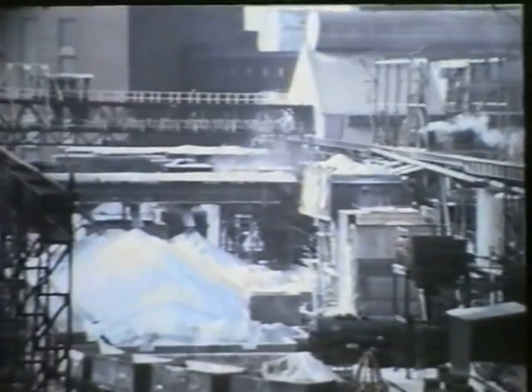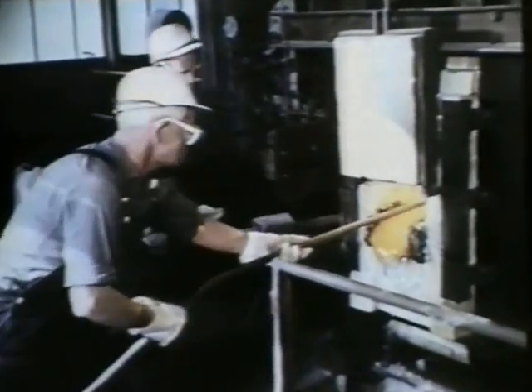Over the road from the bicarb plant, here's something interesting. A heap of green glass, but it's soluble in water, and from it is made one or other of Winnington's many sodium silicate solutions. The silicate glass is made by fusing sand with soda ash in a furnace. It's just been opened up by John Hulse. Joe Goff rakes out the molten glass at a temperature of approximately 1300 degrees centigrade, and soon the fiery, treacly mass is streaming from the furnace.